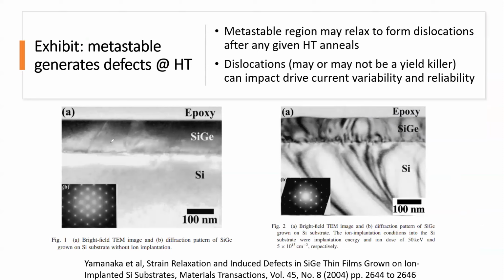And why is that? If you look at this picture, there are two pictures here. This is SiGe, not exactly the same example I mentioned. It's SiGe grown on top of silicon. I'm just using it as a demo that initially does not have much dislocation. Oh, yes, some here, but let's ignore that for now. And then during a high temperature anneal, after implant and then anneal, you can see tons of dislocation popped up. All right, so this is bad.